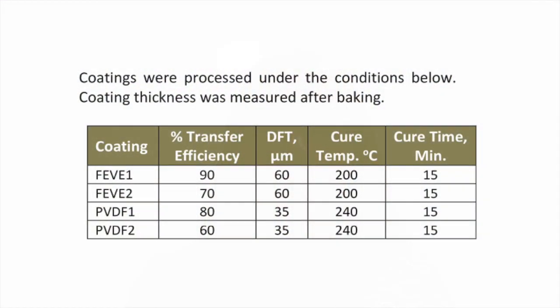And so with the FEVE powder, we assumed overspray was recycled. And so transfer efficiency in one of the conditions was at 90%, and at a second condition it was at 70%. Whereas with the PVDF liquid system, again, these are solvent-based systems, the overspray cannot actually be collected and reused. So the transfer efficiency is lower. And so we assumed in one system 80% and the other 60%.